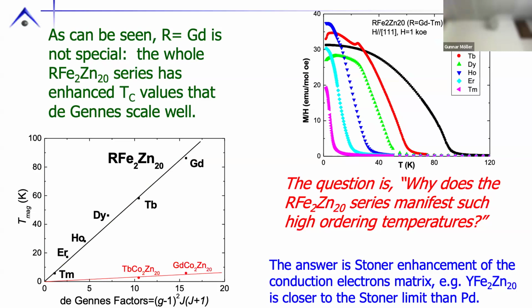So there's nothing special about gadolinium. I can look at gadolinium, terbium, dysprosium, holmium, erbium, and thulium. I see ferromagnetism. And if you plot the ferromagnetic transition temperature versus de Gennes parameter, this is some of the best de Gennes scaling of magnetic ordering you'll see. This is what you'd anticipate from a simple model that says theta should scale as de Gennes factor, mean field. You should have T Curie. And there's very little ambiguity here because it's ferromagnetic, so I'm not changing my wave vector on any of these. Now, I can look at the antiferromagnetism of gadolinium cobalt and terbium cobalt. That's 2. It makes a line, but the line goes through 0, 0, which is a third data point for de Gennes scaling. So you're getting ferro de Gennes scaling here.